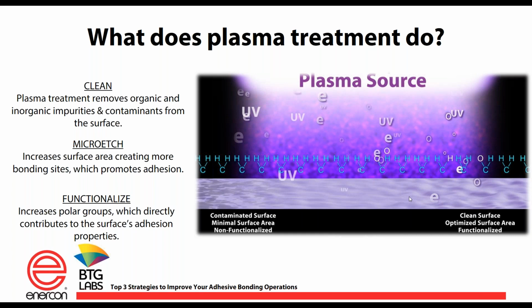Finally, functionalizing the surface, or activating the surface as it's sometimes called. What you're doing is increasing the polar groups on that surface that make it easier to bond to. So you're actually changing the outermost molecular couple of layers and adding functional groups like hydroxyl groups or carboxyl groups if you're talking about flame, and that is what is increasing that surface energy. That's what you're able to measure with BTG Surface Analyst. You're able to see the increase or the decrease in the surface energy that you have, so that you know where you're at and know what your product state is before you bond or print or paint or coat.